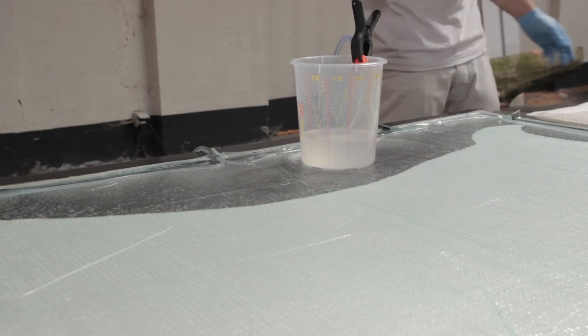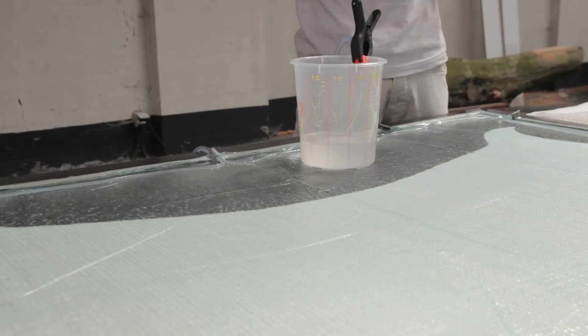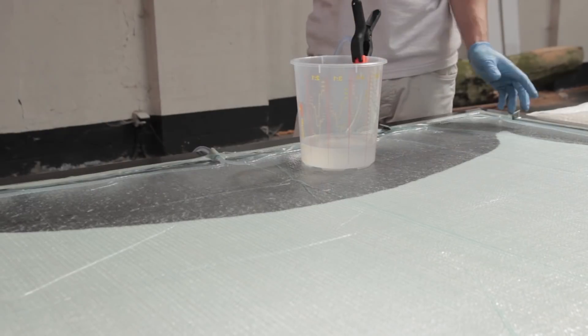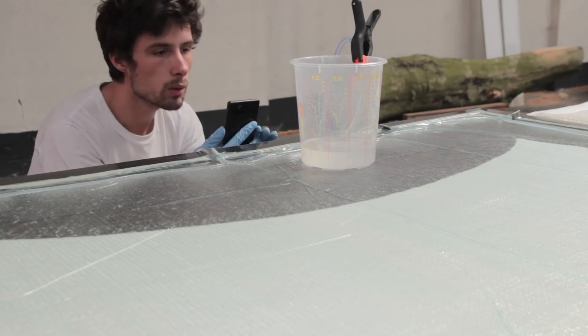As well, you can see I didn't have the time because you only have 25 minutes to mix everything and start infusion, so I didn't have the time to degas the resin. All the air bubbles you see here are caused by not degassing the resin.